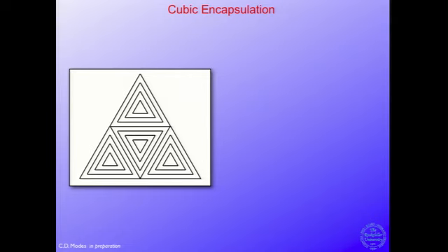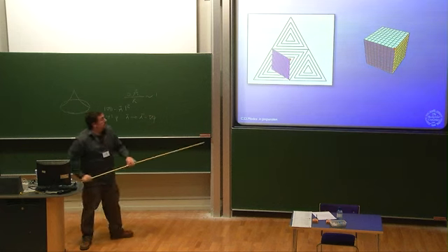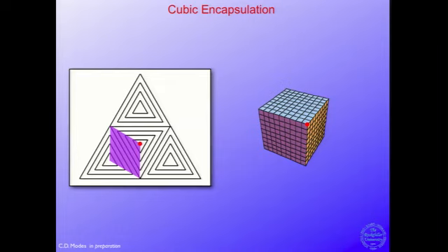So if you take a texture like this, where you have 4 joined triangular defects, this is going to make a cube. The way to imagine how this works is you say that this defect in the center becomes this corner of the cube. And then this region, from this defect to this defect, and laterally from this boundary to this boundary, becomes this face of the cube.